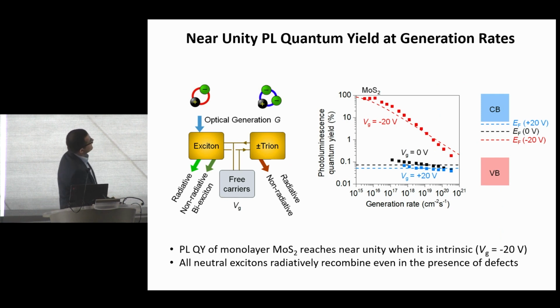And so by doing quantitative measurements, we can measure the photoluminescence quantum yield as a function of generation rate for different gate voltages. Now, when you're thinking about these gate voltages, the substrate was a very thick oxide for these measurements. You have to think about where the Fermi level is. In the case of moly sulfide, as made, as processed, the material is known to be N-type because of the native defects, and the Fermi level is close to the conduction band. If you apply a positive gate voltage, the Fermi level moves further close to the conduction band. If you apply a negative voltage, you can move it to mid-gap. And so based on the data that we got, we were able to come up with a very simple model.